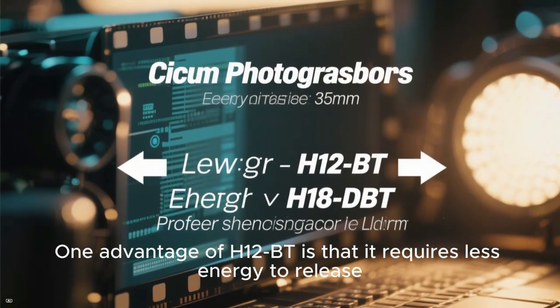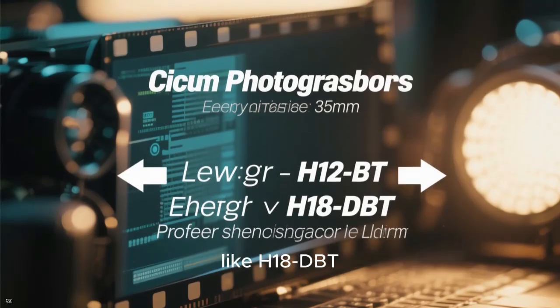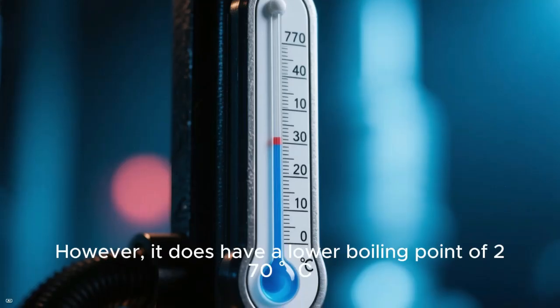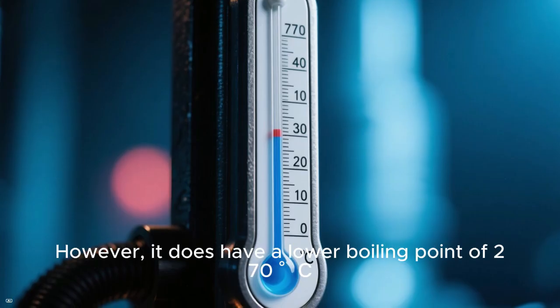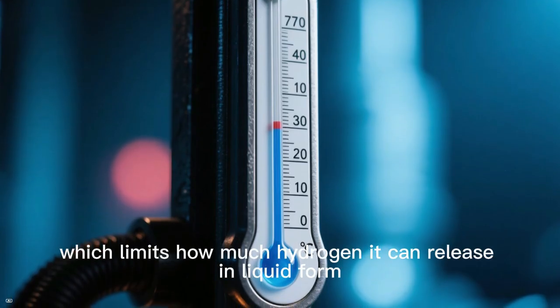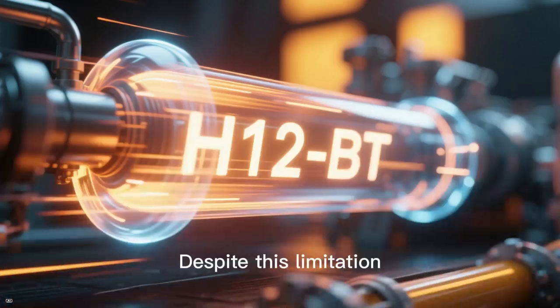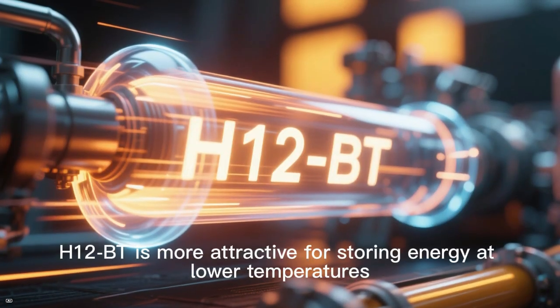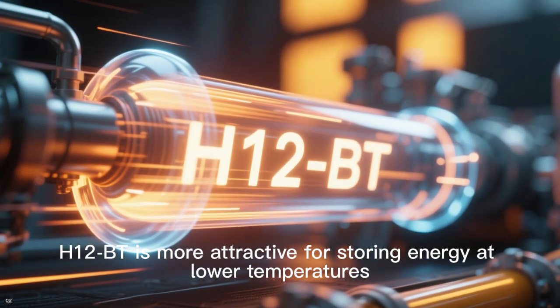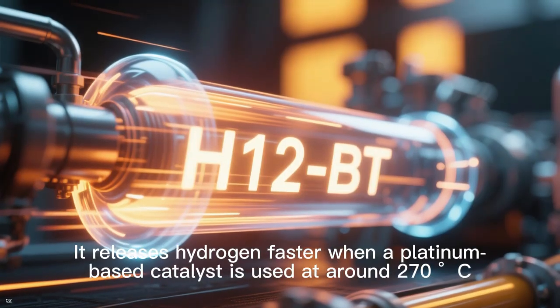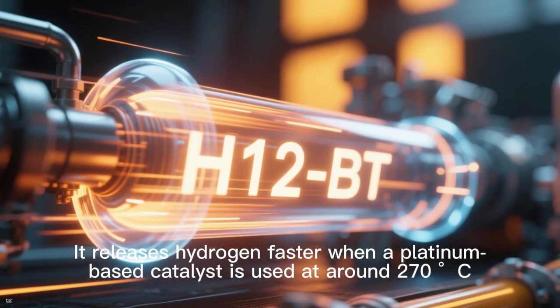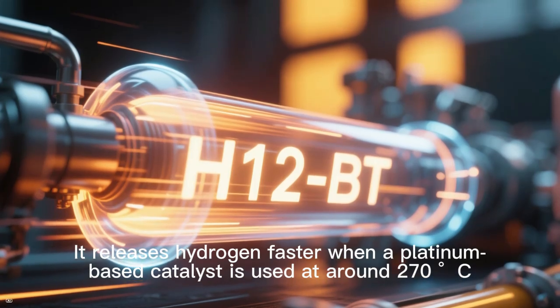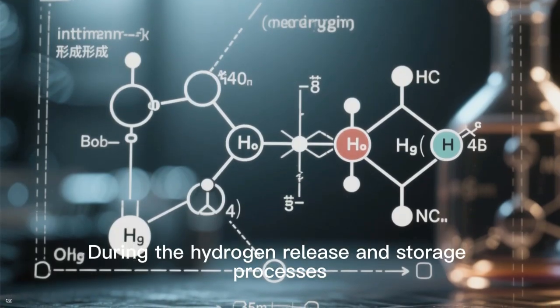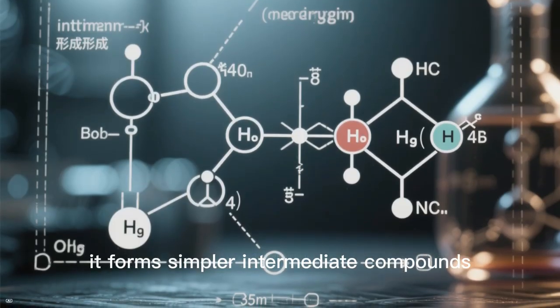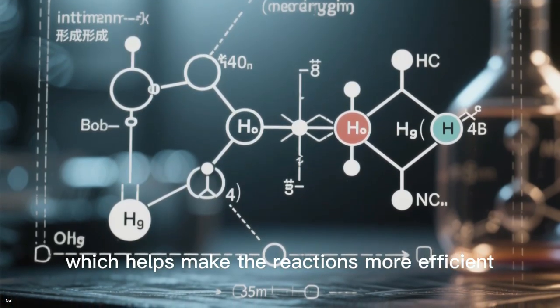One advantage of H12-BT is that it requires less energy to release hydrogen compared to some other carriers, like H18-DBT. However, it does have a lower boiling point of 270 degrees Celsius, which limits how much hydrogen it can release in liquid form. Despite this limitation, it is more attractive for storing energy at lower temperatures. It releases hydrogen faster when a platinum-based catalyst is used at around 270 degrees Celsius. During the hydrogen release and storage processes, it forms simpler intermediate compounds, which helps make the reactions more efficient.